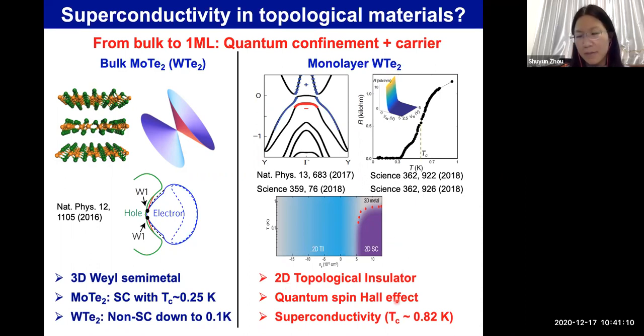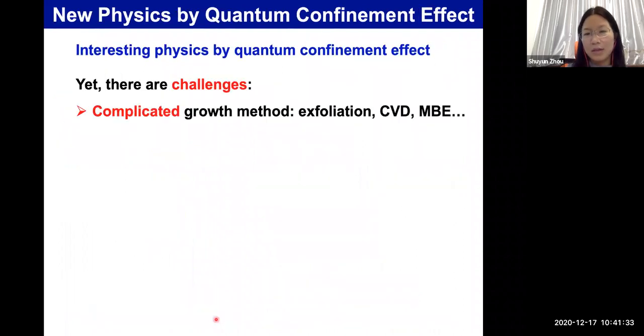In addition, by reducing the sample thickness to monolayer, superconductivity with a transition temperature of 0.82 Kelvin has been reported. So this 0.82 Kelvin is much higher compared to the bulk, below 0.1 Kelvin. However, it's still quite low, and there are also other challenges.